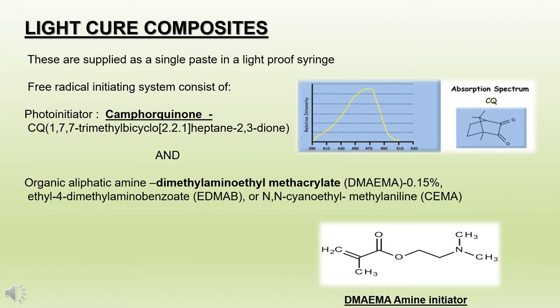Light-curable dental composites are supplied as a single paste contained in a light-proof syringe. The free radical initiating system, consisting of a photosensitizer and an amine initiator, is contained in this paste. As long as these two components are not exposed to light, they do not interact. However, exposure to light in the blue region, wavelength of about 468 nanometers, produces an excited state of the photosensitizer, which then interacts with the amine to form free radicals that initiate addition polymerization.